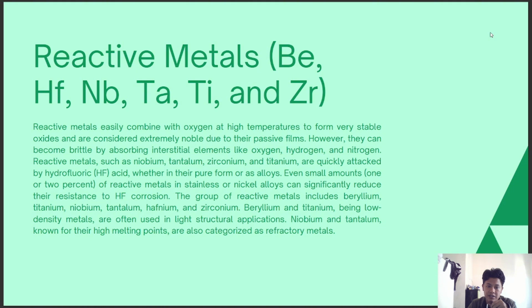Reactive metals such as niobium, tantalum, zirconium, and titanium are quickly attacked by hydrofluoric or HF acid, whether in their pure form or as alloys. Even small amounts, 1 or 2% of reactive metals in stainless or nickel alloys can significantly reduce their resistance to hydrofluoric corrosion. The group of reactive metals includes beryllium, titanium, niobium, tantalum, hafnium, and zirconium.